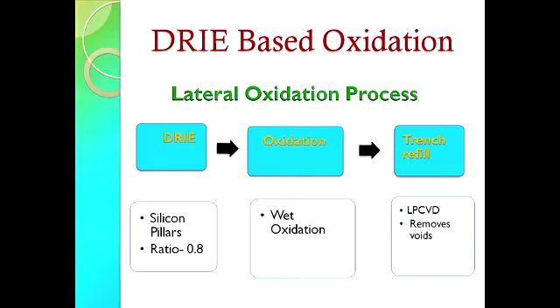And that's why we use deep reactive ion etched based oxidation, which is basically a lateral oxidizing process instead of the usual ones where the oxidation happens vertically. So here in the first step we form silicon pillars, that is high aspect ratio silicon pillars with a ratio of 0.8, and this ratio is the ratio of silicon pillar width to the trench width. So if we have a ratio of 0.8, then we can have good oxidation.